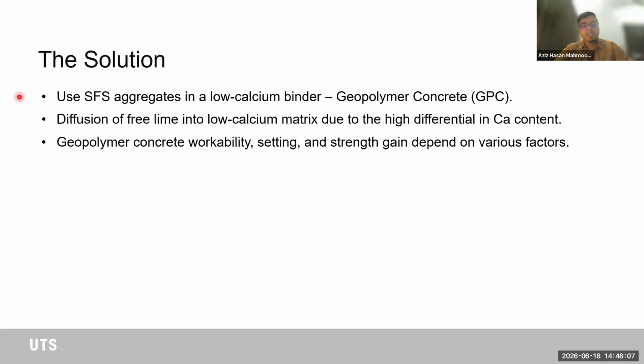The good thing about these products is that they are very amorphous in structure, so you can activate them using some sort of alkali. So we have chosen sodium hydroxide and sodium silicate to activate. But the key point here is now we are trying to design a concrete which doesn't use any cement, doesn't use any natural sand, doesn't use any natural aggregate or stone. So every component of the concrete comes from industrial byproducts. The only chemical that we used is the activator.